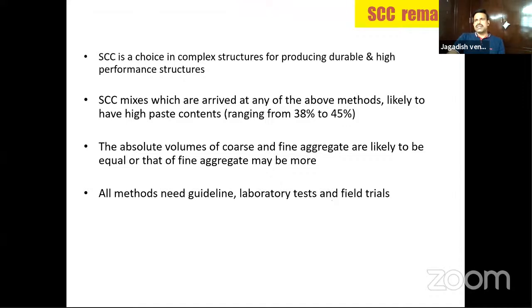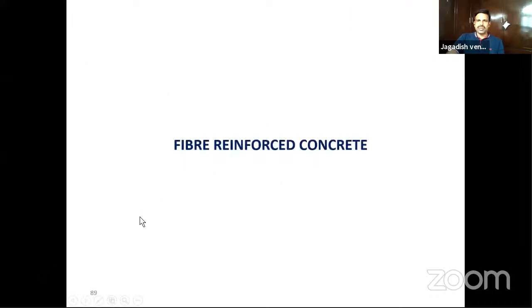And SCC mixes particularly have high paste contents. In normal concretes, typically the powder content is around 26, 27, 28%. But in case of SCC mixes, the powder content goes up to 38 to 45% when you look into the volume fraction of the paste. And as I mentioned, the coarse and fine aggregates have equal volumes. But anyway, whatever mix you make should need guidelines, laboratory tests, and field trials. Very, very important.